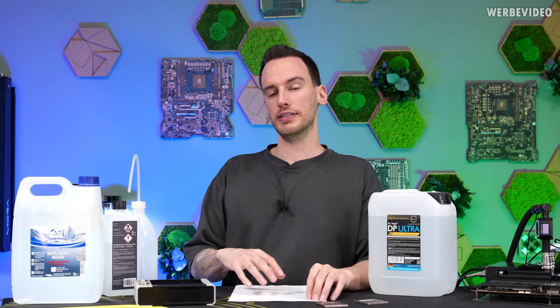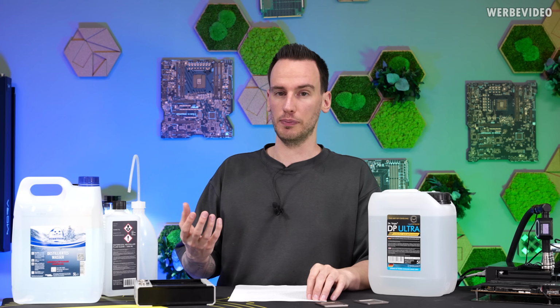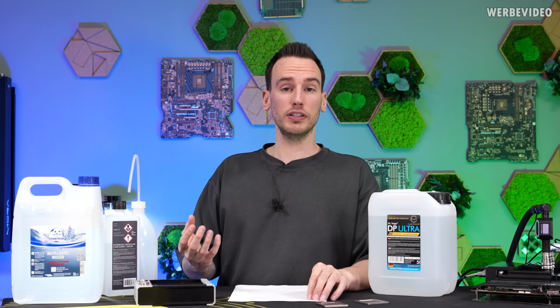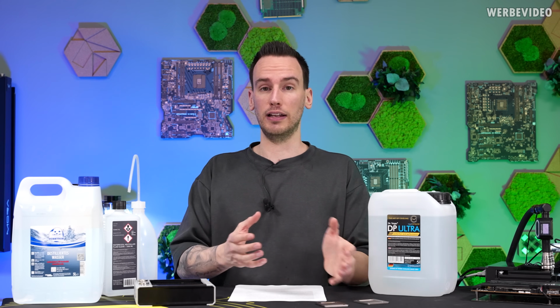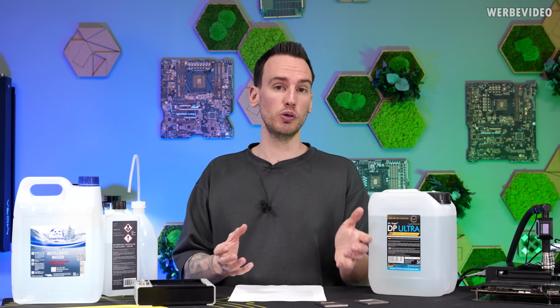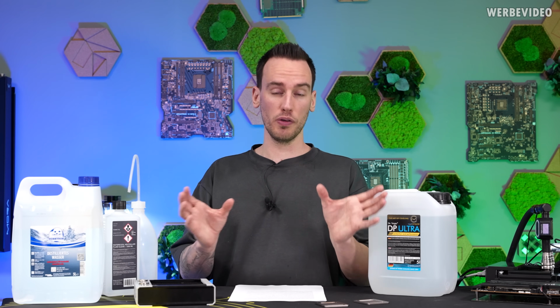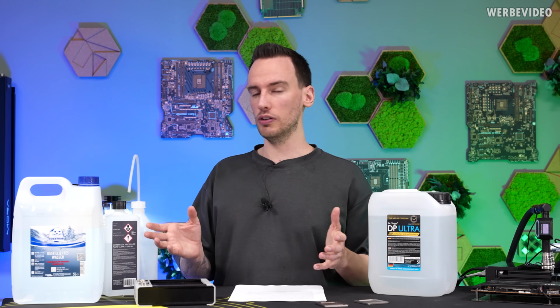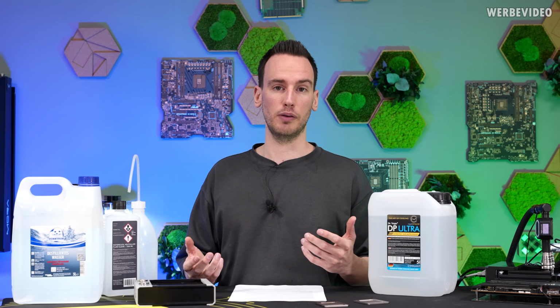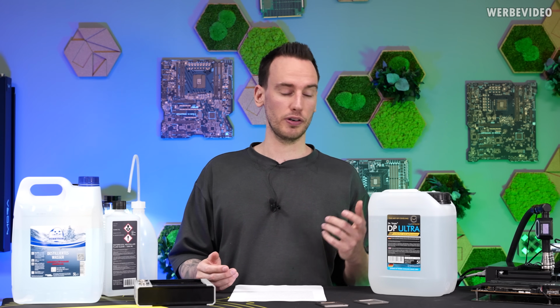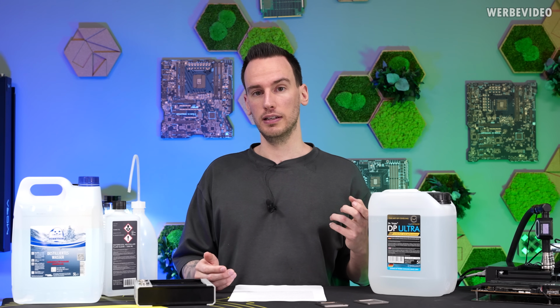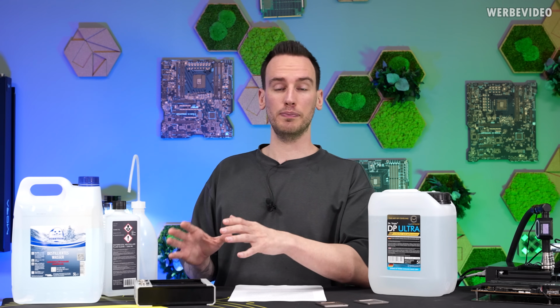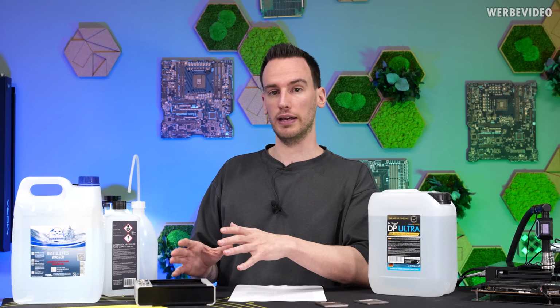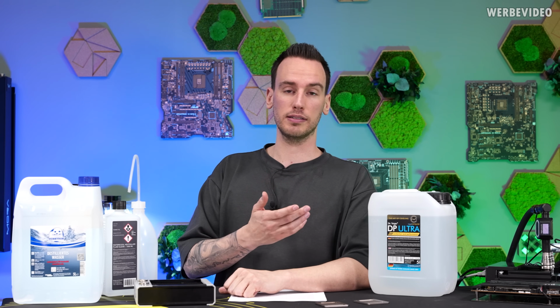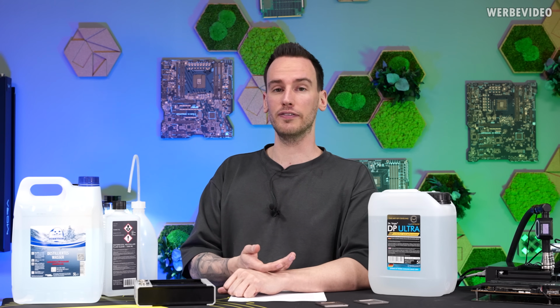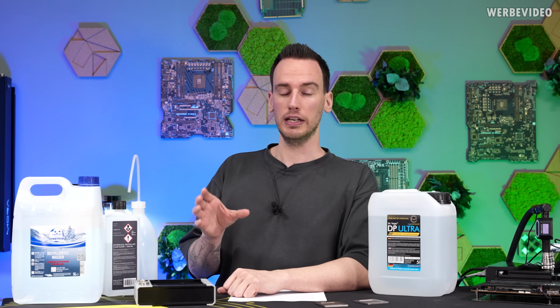These corrosion inhibitors have to be selected according to the materials that are being used in your loop. You can even use a loop where you mix copper and aluminium. That also works fine if you have the right coolant that can work with both of the materials, which is usually not the case for all the coolants that are being used in our industry. For example, the DP Ultra is not made for that. But for most of the coolants, if you use a copper-based loop without aluminium, then let's say the DP Ultra or coolants 702 or Corsair XL5, those common liquids are usually very good.